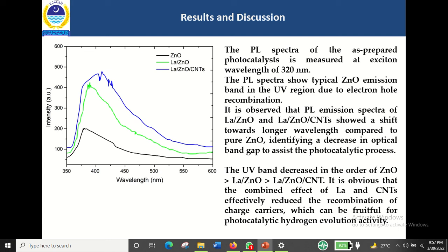It is also observed that the PL emission spectra of the lanthanum ZnO composite and the lanthanum ZnO CNT composite show a shift towards the longer wavelength as compared to pure ZnO, which identifies a decrease in optical band gap, and it is supportive to the photocatalytic activity of the catalyst under the visible region of the light spectrum.